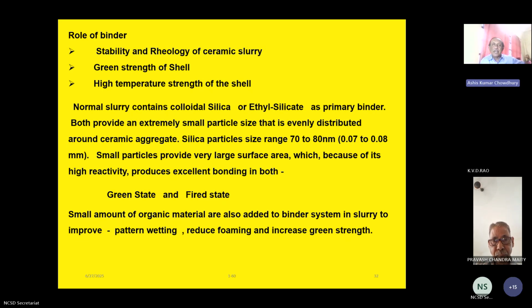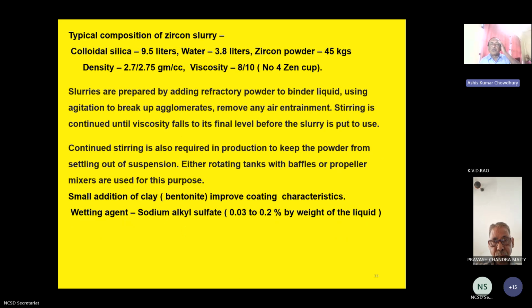Typical composition of zircon slurry, which is being used as a first coat material, basically it will always be there for binding: colloidal silica 9.5 liters, water 3.8 liters, zircon powder 45 kg. Density should be around 2.7 gram per cc, viscosity 8 to 10 number 4 cup.